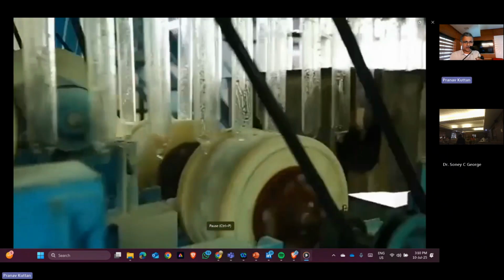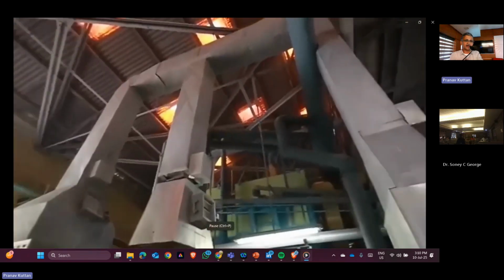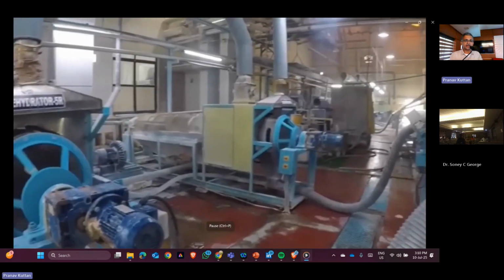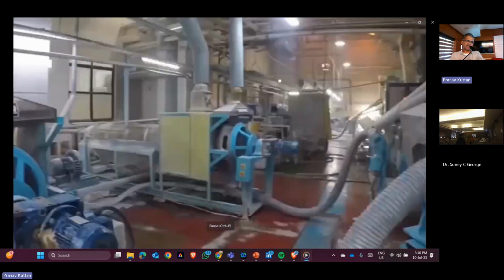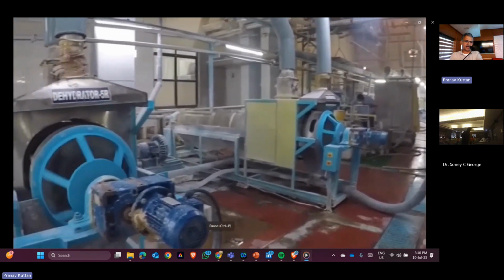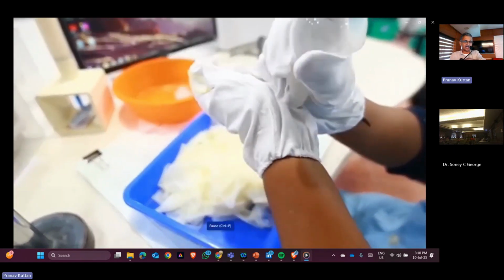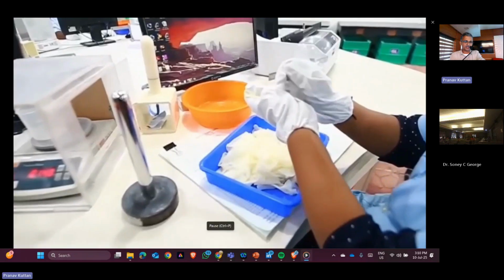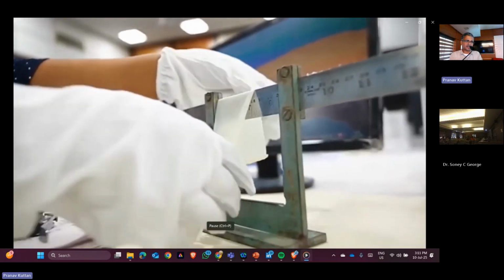So this is rinsing, water washing, hot water washing, soap solution washing, and then it's going for the drying. Here the stripped condoms are dehydrated from the slurry, and then they are taken to the vulcanizing chamber or a washing machine dryer, where it is dried and then heated, and then it's tested for the quality parameters, the half product testing, whether it's having any production issues, and then the length and the dimensions are being measured, and then it is going for the electronic pinhole testing.